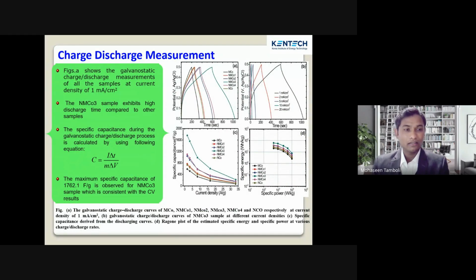Then we again checked this material. We again measured the specific capacitance using the charge discharge process, and we received the same results as from cyclic voltammetry. The maximum specific capacity of 60% nickel substituted MnCO2 shows 1762 farads per gram, and as compared to all the other electrodes, the 60% nickel substituted MnCO2 pore sample shows good performance and good electrochemical properties.